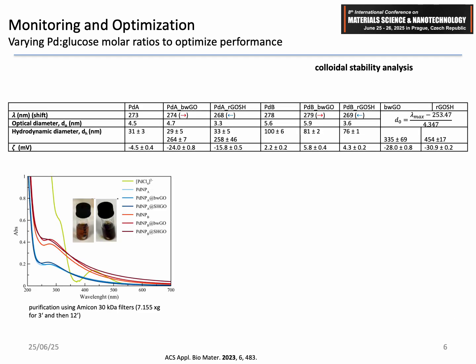To tune the performance of our palladium nanoparticles, we adjust the palladium to glucose ratio, producing two populations: the so-called palladium A, smaller particles, and palladium B, with larger particles. The formation was monitored by UV visible spectroscopy. Initially we can see this green line with the spectrum showing a peak at around 420 nanometers, and this is due to the ligand to metal charge transfer in the palladium complex. As the reaction progresses, the solution changes color from yellow to dark brown, and this also corresponds to the disappearance of this band and the appearance of the plasmonic peak in the UV around 270.